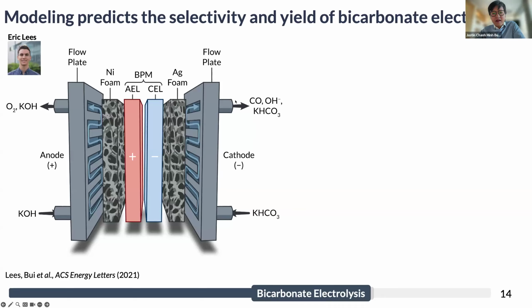That allows you to generate the CO when the bicarbonate reacts at that cation exchange layer, liberates the CO2, forms the CO on the silver foam, and that CO then can get taken out. On your anode side, you're just doing oxygen evolution. So that's just your counter reaction to balance that bicarbonate electrolysis.